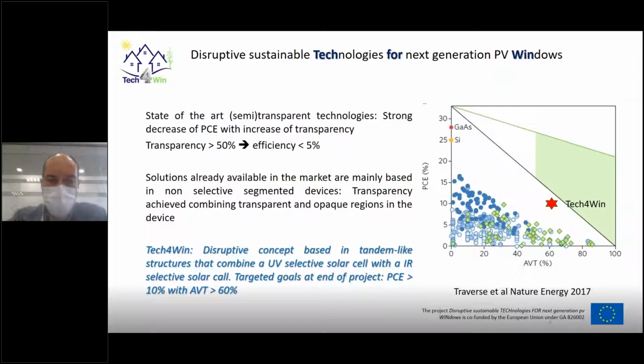In Tech4Win, what we propose is a disruptive concept based on the integration of a tandem-like structure in the window that combines an ultraviolet selective solar cell with an infrared selective solar cell. The targeted goal that we are defining is to demonstrate at cell level an efficiency higher than 10%, combined with a transparency higher than 60%. As you can see here, the red star would be the result of Tech4Win in front of the state of the art.